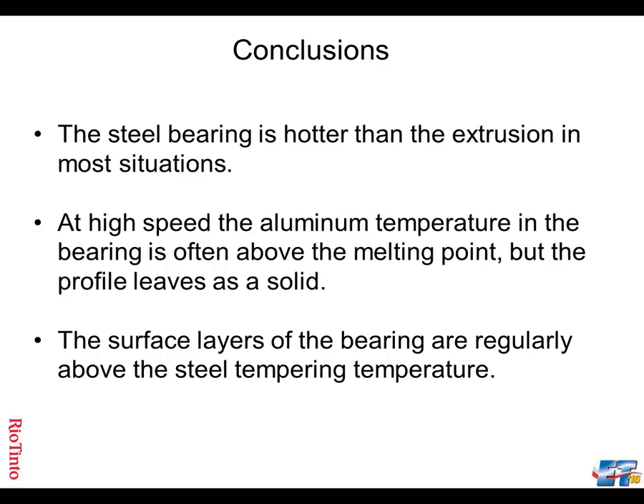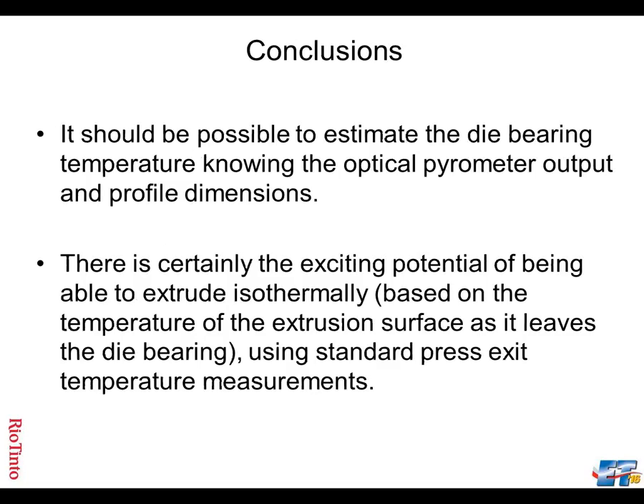This is surprising. At high speed, the aluminum temperature in the bearing is often more than the melting point. Yes, we have measured 660, 670 Celsius, which is well above the alloy solidus, the melting point, but the profile does still come out as solid because the conduction, it freezes so fast. The surface layers of the bearing are regularly above steel tempering temperature, yes.